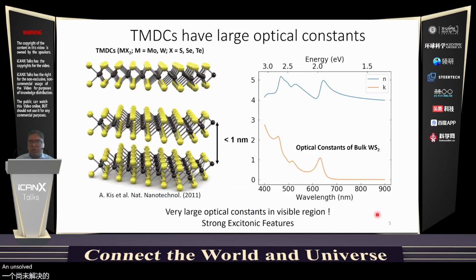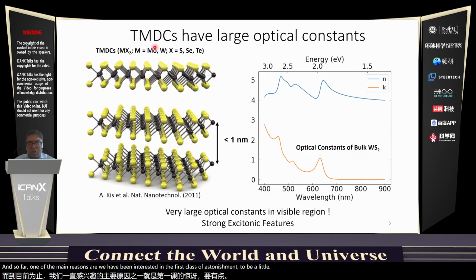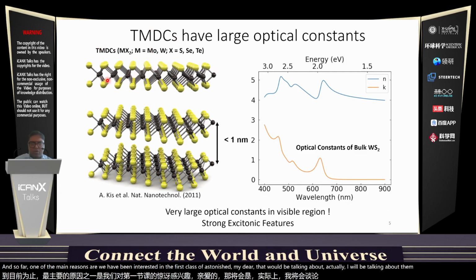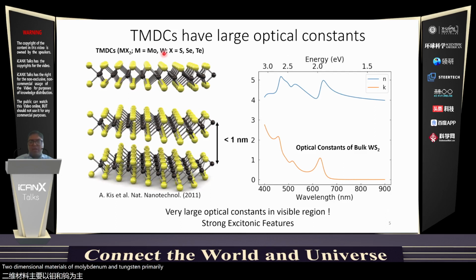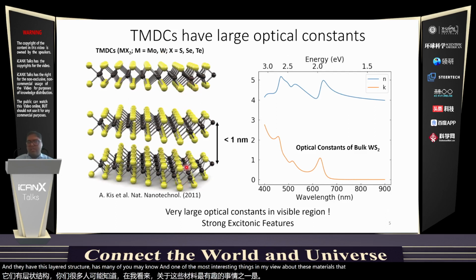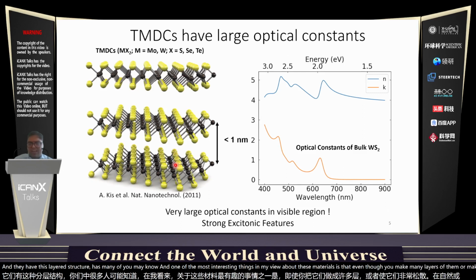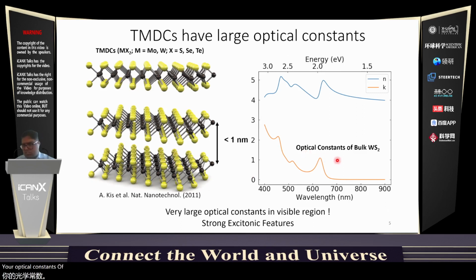One of the main reasons we have been interested in the first class of excitonic materials that I'll be talking about, and I will be talking about them for most of this talk, is these TMDCs, the transition metal dichalcogenides, semiconducting two-dimensional materials of molybdenum and tungsten primarily. They have a layered structure, as many of you may know. One of the most interesting things in my view about these materials is that even though you make many layers of them, or make them very thick or electronically bulk in nature, their optical constants are still highly dominated by excitons. You can see that in their optical dielectric function. This is of bulk WS2, for example.